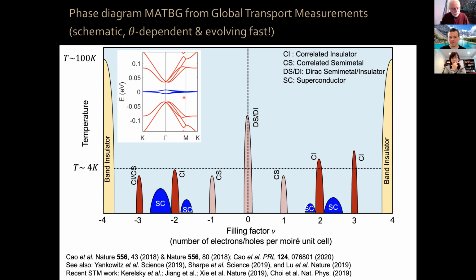Now, in these flat bands, due to the spin up, spin down, valley K, K prime degrees of freedom that I told you about from electrons in graphene, starting from charge neutrality, from zero energy, we can put up to 4 electrons per Moiré unit cell, or we can empty 4 electrons, or put 4 holes, per Moiré unit cell. So we can put a total of 8 electrons per Moiré unit cell in the system. We typically call that filling factor nu, which tells you the number of electrons or holes per Moiré unit cell that you have in your system. Zero is charge neutrality.